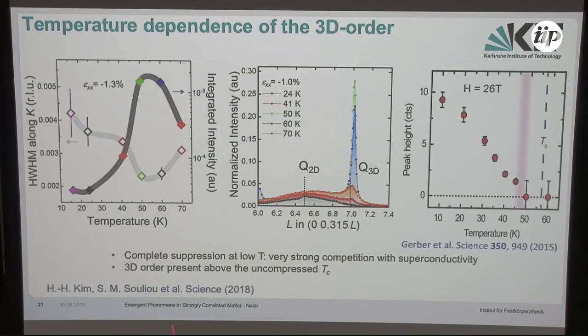So it means that the competition with superconductivity is also very, very strong, because this is the intensity versus temperature. At low temperatures, we cannot detect it anymore, and it really shoots up at the TC of the sample, which again is consistent with the magnetic field data. But now, instead of completely suppressing superconductivity and inducing the peak at low temperature, we can suppress it a bit and induce this long-range order much stronger.